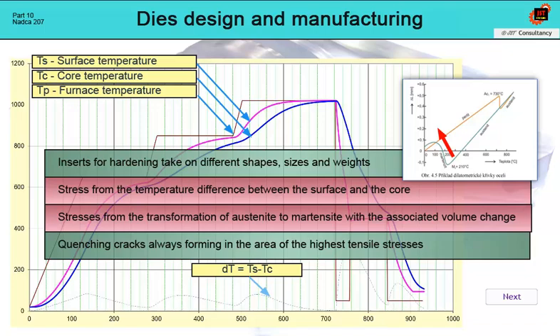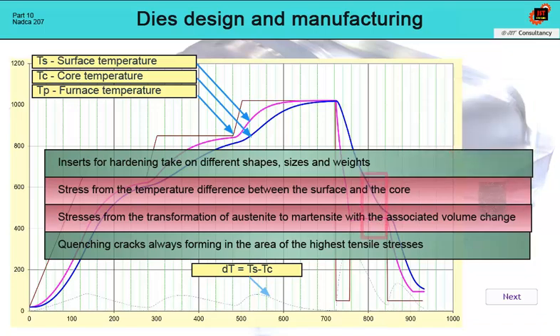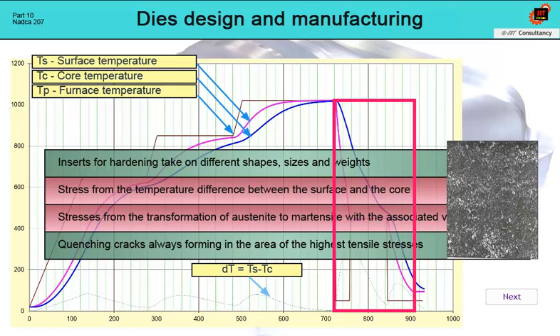But it must be said that in order to achieve good impact strength results, the speed of cooling is an absolute priority, and therefore the heat treater must cool as quickly as possible, regardless of possible distortions or cracks. It is therefore up to the designer to treat the shape of the inserts to survive hardening.